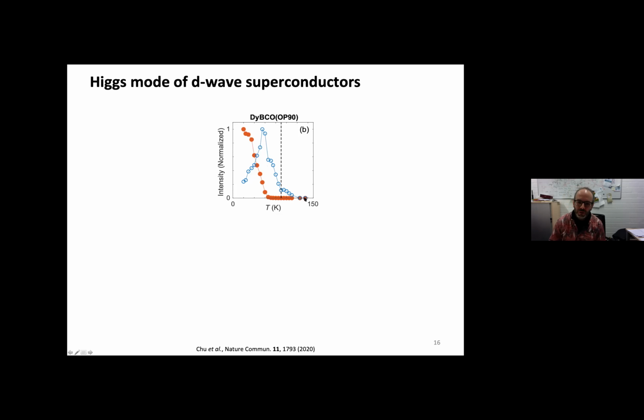And if we do so, then you see this third harmonic generation is really setting on strongly only below TC, and you see there is no strong resonance feature on these traces, which is in full agreement with a heavily damped Higgs mode that has no resonance condition, because we have a gap that is continuous from 0 to delta max that is basically setting in below TC.